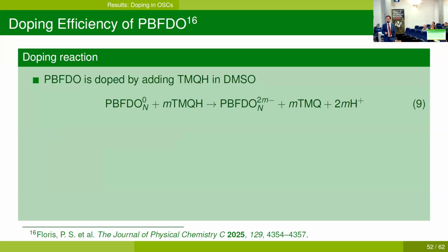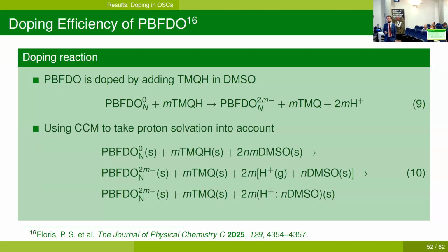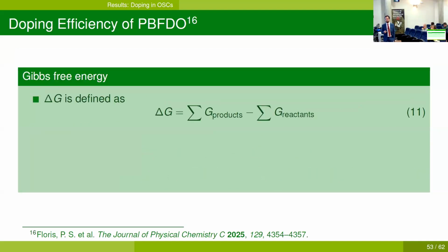So the doping reaction of this polymer looks like this. We add durohydroquinone, or TMQH, to the polymer, and durohydroquinone becomes duroquinone and releases protons, and the polymer is doped. It has received 2 electrons from each molecule of dopant. So we see that we have some protons here in the gas phase, and we actually need to take account of that using the cluster continuum model. So we need to take into account N molecules of solvent explicitly, which allows us to calculate now the actual delta G of the doping reaction.